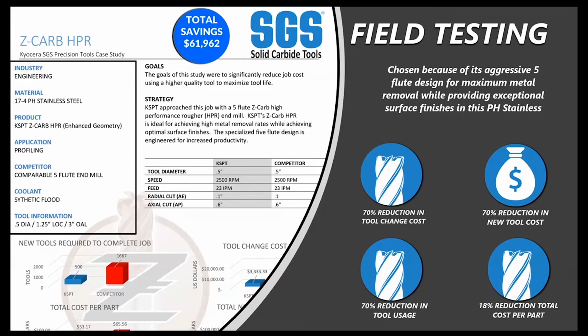So here's another case study based on a cost savings that we offered a customer in 17-4 PH stainless. They were using a competitor's 5-flute end mill with a trochoidal tool path. Both end mills were 1/2 inch diameter, programmed to take 600 thousandths axial depth with a radial engagement of 20% or 100 thousandths in this case. Tool cost was similar and running parameters stayed the same.